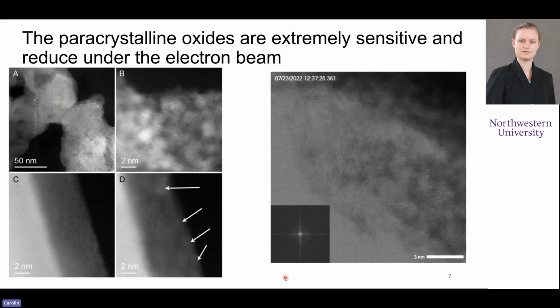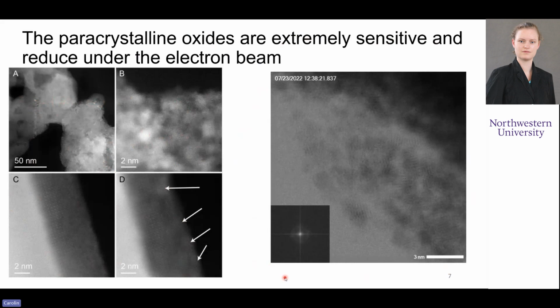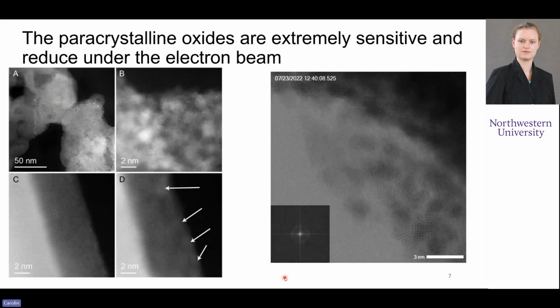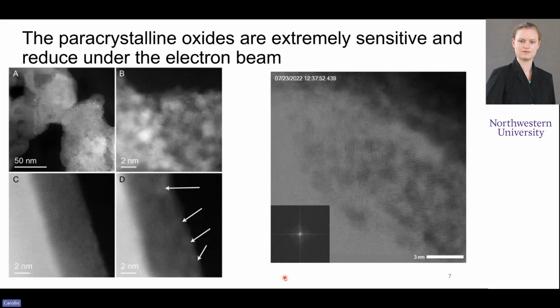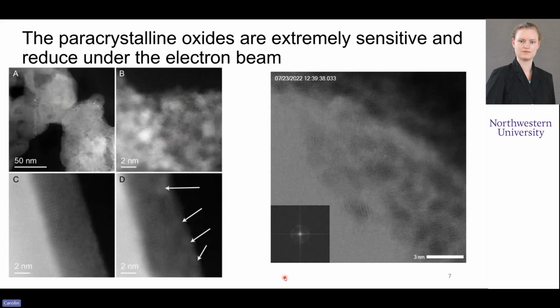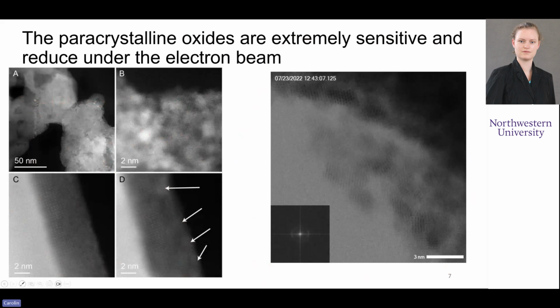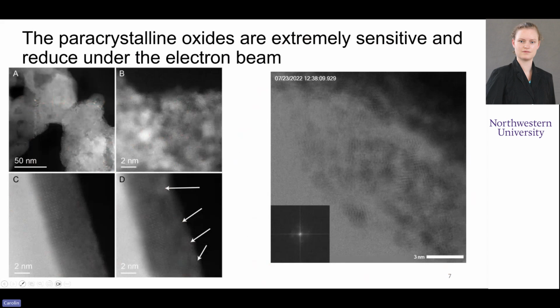And this turns out to be really critical because there's a lot of conflicting opinions in literature as to what happens to these materials, how they form. Some reports show that there are crystallites on the surface. Some claim the surface is completely amorphous. And none of them have a good discussion on beam damage. And so if you're not really, really careful when you look at materials like this, you can miss details like this, which by capturing every single frame and putting it together like this, we're able to visualize in a way that wouldn't be possible otherwise.